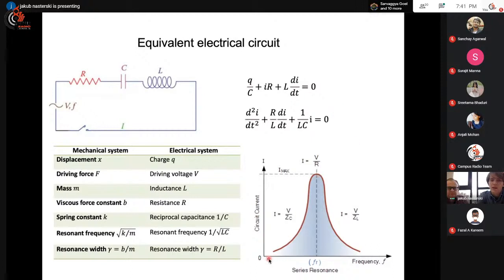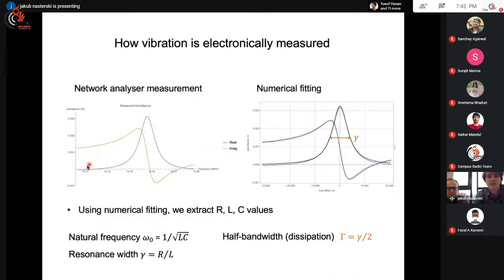You can see that when the frequency of the current is close to the natural frequency of the system, we also have this resonance peak. And the constants have their equivalences. So the resonant frequency here is 1 over square root of LC. The gamma is R over L. So this is the actual reading from one of our instruments. We applied the alternating voltage close to the resonance frequency of our crystal, which is around 13.3 megahertz. And you see that the current is maximum at a certain frequency.